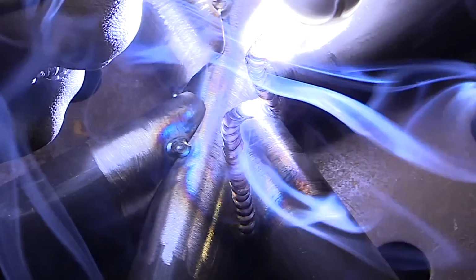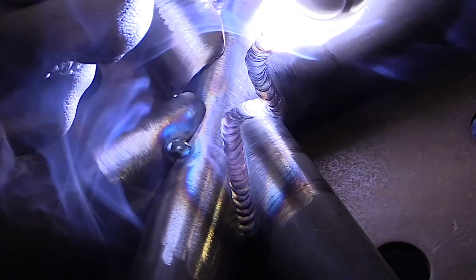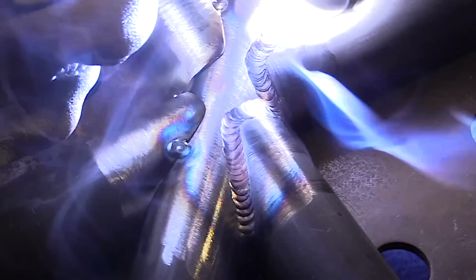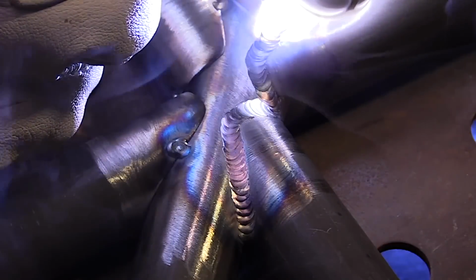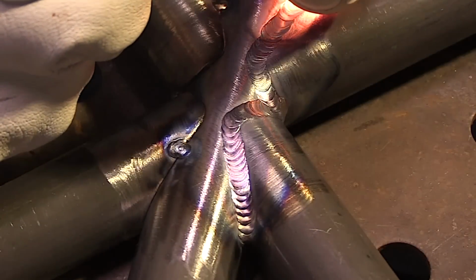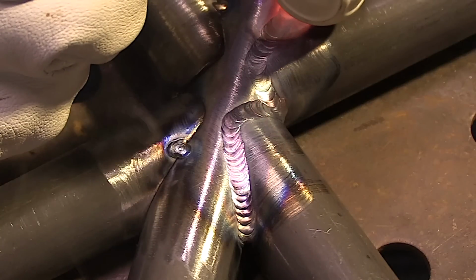In this video right here, I'm using a Furick Ceramic 12, and that provides a nice big envelope of argon, a nice big shielding area. Prevents discoloration, but also gives you a little bit of leeway on how far you can dip the hot tip of your rod away from the puddle and still keep it shielded. I'm using a .045 filler metal, ER70S-2. That is usually a really good choice for this wall thickness chromoly.